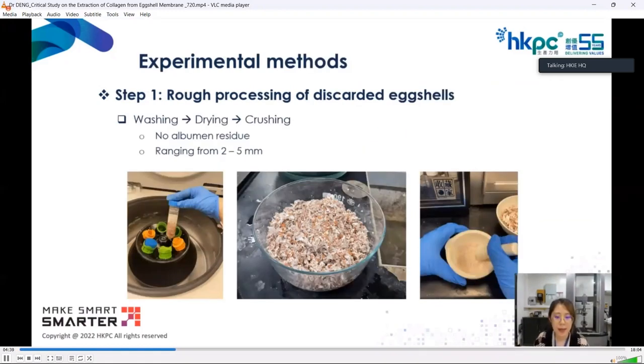Here are the experimental methods to extract collagen from eggshell membrane. The raw material, eggshell waste, was obtained from our partner, Lintai Hong Kong Fresh Liquid Egg Limited. This company has a history of more than 60 years, and they are in the business of fresh egg products. In this study, all raw material was obtained from our partner. Firstly, eggs were washed with water before being separated into egg white, egg yolk, and eggshell with an egg-breaking machine. The collected eggshell waste is then ground in a centrifugal mill to particles with a diameter of 2 to 5 millimeters.